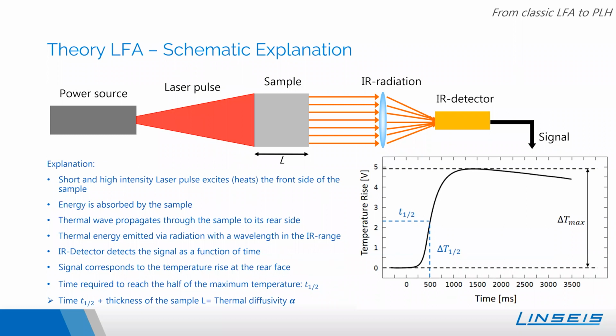So let us start with the theory of the LFA. Its schematic explanation is shown on this slide, and the most important parts are the power source, which is a neodymium YAG laser, which is used to heat up the front side of a sample using a very short heating pulse. And this energy of the pulse is absorbed by the sample. Afterwards, a thermal wave propagates through the sample to its rear side, where this thermal energy is emitted via radiation in the infrared range. This infrared signal is detected by an infrared detector as a function of time.